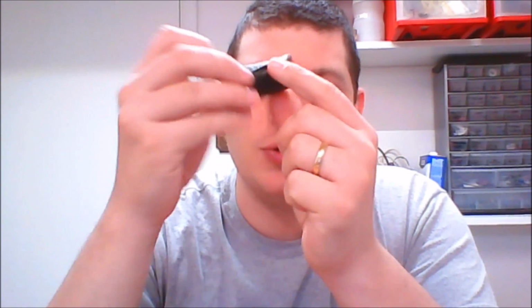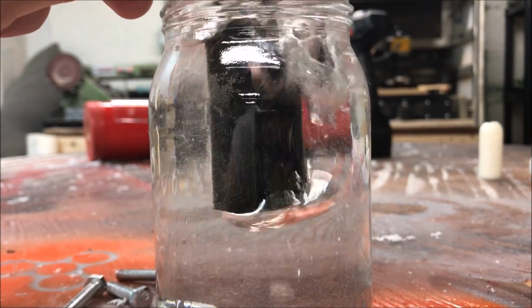The TPU was odd. It seemed to hold air at these seams here, but it was losing everything from the bottom. I actually went and printed another one to see if it was just a defect with the print, but it's the same. For some reason, something about this right here causes it to leak. I don't know if it's a problem with the slicer, where it just lined up layers and then air happens to be able to escape, or if that's just the direction where the material is weaker. But I still could not get them to hold pressure. I could probably do quite a bit of investigating with the TPU, and you might actually still be able to get this to hold pressure since it wasn't porous in this direction here.